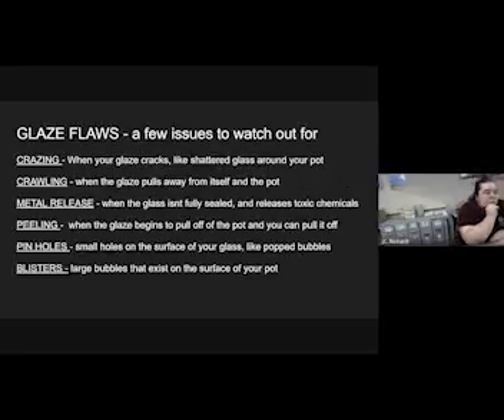Glaze flaws, a few issues to watch out for. So crazing is when your glaze cracks, like a shattered window all around your pot. Crazing is kind of funny because you can actually hear it while it happens. So we pull a piece of pottery out of the kiln and we put it on the shelf, and you're just sitting there next to your pottery, and all of a sudden you hear these little ting, ting, ting, and your pot is making that sound because it's crazing, because the glaze did not fit the clay body. The clay body did not shrink enough for the glaze.